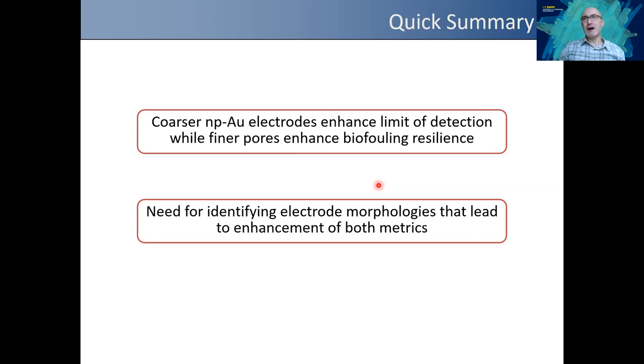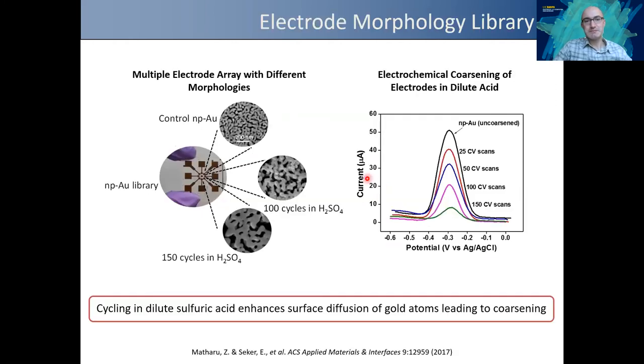Again, we have the same issue. How do we find those morphologies? You can test a lot of different electrodes, but it would be very time consuming and you would have repeatability issues. So we thought that we can again use this high throughput method where we have a multiple electrode array, but this time we used electrochemical cycling, where you have your electrode in sulfuric acid, and you just cycle it with cyclic voltammetry in sulfuric acid, which again enhances the surface diffusion of gold atoms and leads to coarsening, but it's very controllable because you can just adjust it with the number of cycles that you are going through. And you can basically have multiple electrodes array on one chip with different morphologies.